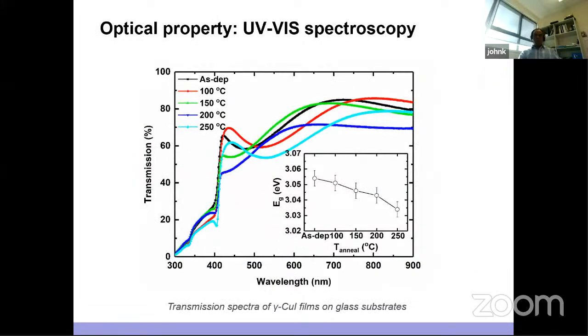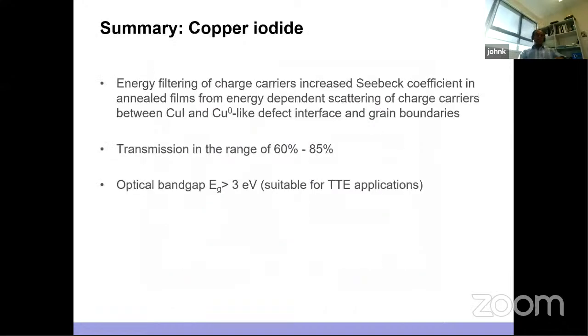Obviously, if you look at the optical properties, it is really transparent, from 60 to 80%. And in fact, it gets better around 100. If you anneal it at 100 degrees C, it's already transparent around 70, 80%. So it's really transparent, you can see through. The band gap changes from 3.03 to 3.05 eV, which is quite good. So it is really a transparent thermoelectric material. So in summary, we can see the energy filtering effect, which is a key factor, and which explains the copper iodide, copper-zero-like defect interface along the grain boundaries.